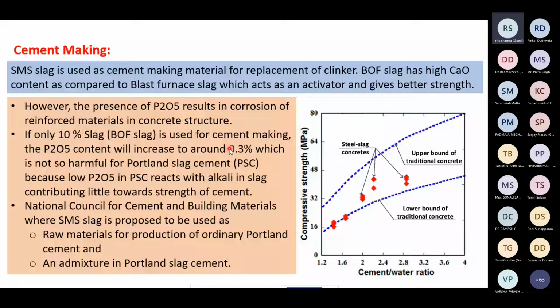So around 10% of slag they are utilizing, and the remaining is the original material. By using that, they are consuming the least amount of raw material for making the cement. So if the P2O5 content is less than 0.3%, which is not so harmful for the Portland slag cement, that is the PSC. Usually the common cement we know as Portland cement. So for that, 0.3% of phosphorus is allowed, and companies are maintaining that particular level.